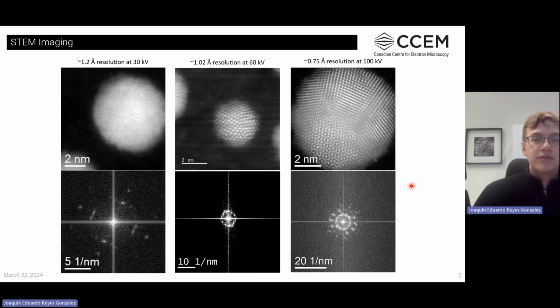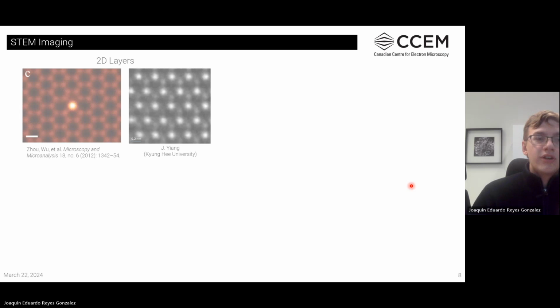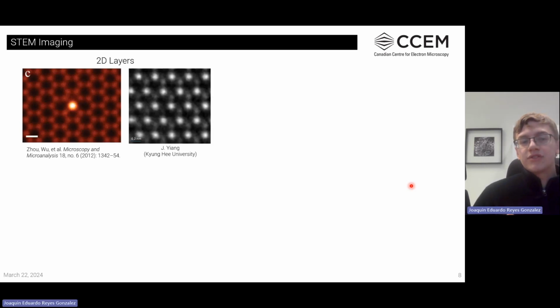As for what we are actually using this for, well, when we actually look at a real system, we can look at things like two-dimensional materials, so samples that are very, very thin, let's say 1 atom, 3 atoms, depending on how you define your 2D material. So you can look at something such as graphene, in which case that's our figure over here. That's graphene with some defects inside of it. Or you can look at a 2D material such as a two-dimensional transition metal dichalcogenide. That was actually imaged here on our own system, but the sample came from Kyung Hee University in Korea.